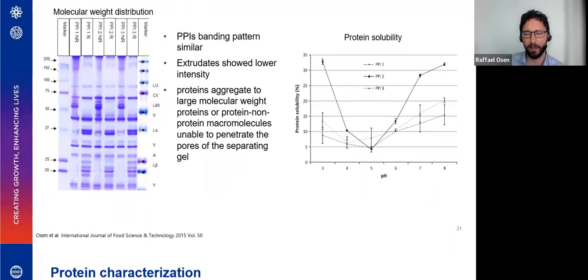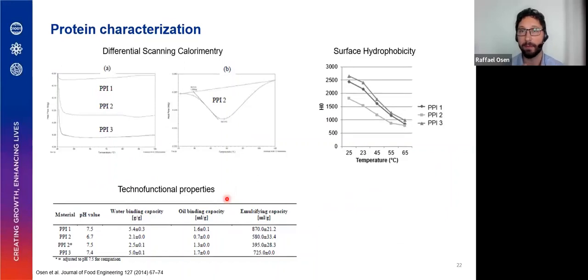Then next we looked into the denaturation, thinking, okay, if the solubility is higher, this could be indicative of a not fully denatured protein. The data shown here, the differential scanning calorimetry graphs, basically reassured us in that thought. For protein number 2, we found an endothermic peak. In comparison, protein number 1 and number 3 did not show any of these endothermic peaks. So this shows that protein number 2, as a result of the processing history, was not fully denatured and therefore had a higher protein solubility.